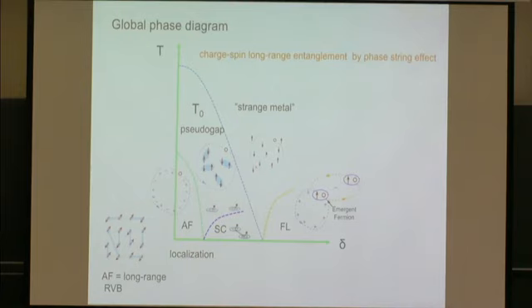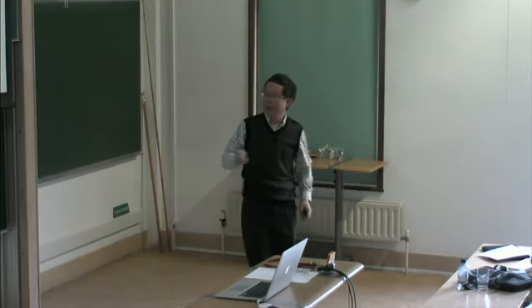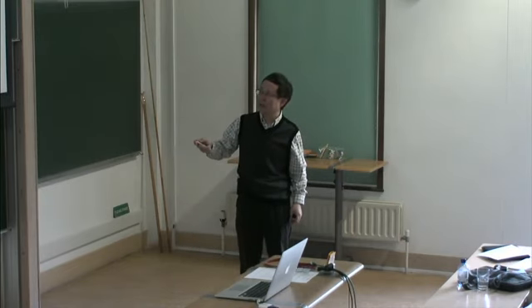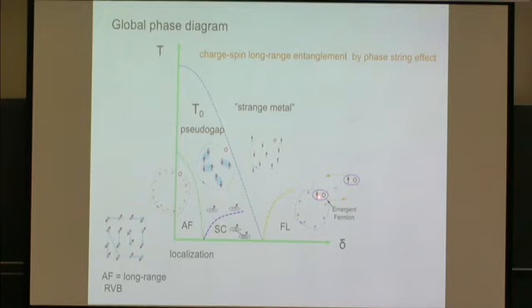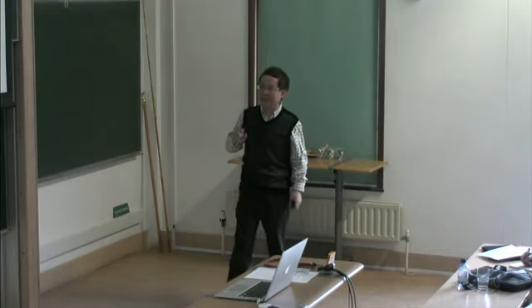But this state at zero temperature is not stable because of the huge fluctuation in kinetic energy. So it turns out the spin and the hole would like to bond together, such that at each hopping, the hole will exchange with this backflow spin, such that the sign structure becomes trivial, all the same sign. And therefore, they will recover a fermion, a quasi-particle with the same quantum number, and the two of these objects just satisfy fermion statistics. So this is roughly what happened here.